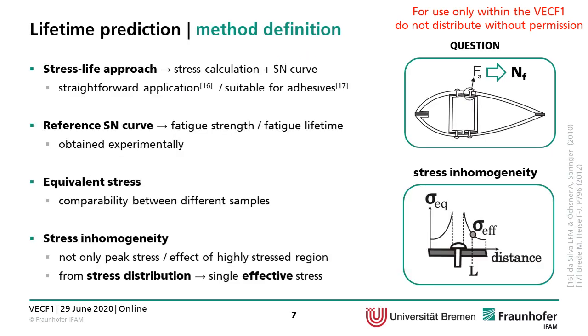For the lifetime prediction, the method was defined as shown here. So we use the stress life approach, which requires stress calculation, in this case using finite element analysis, and an SN curve, which is obtained experimentally. It has a straightforward application and has been proven suitable for adhesives in many projects. And a reference SN curve is necessary. This reference SN curve shows the relation between fatigue strength and fatigue lifetime. Equivalent stress is necessary because